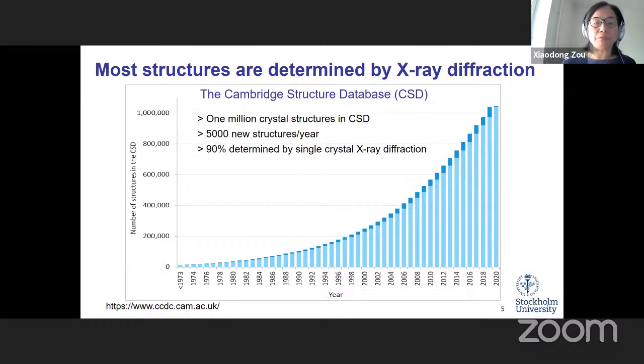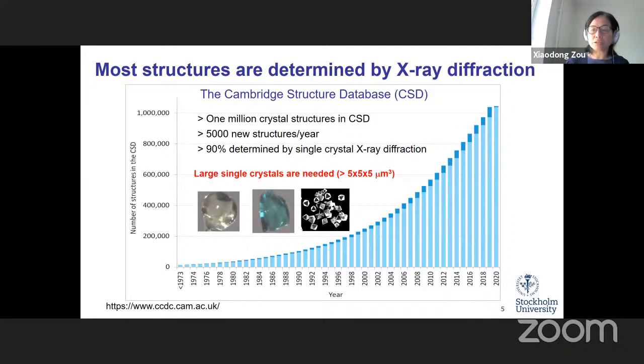There are more than 1 million crystal structures in the database, and more than 5,000 new structures are deposited every year. This is just the part of organic crystal structures. More than 90% were determined by single crystal X-ray diffraction, so it is a very important technique for structure determination. But there is one drawback of the method: it needs large crystals. Large means a few micrometers in size in different dimensions, and for more complicated structures, the dimensions need to be larger. Growing large single crystals is always a problem, and that has prevented structure determination of many new materials that have probably been synthesized but whose structures were difficult to know.